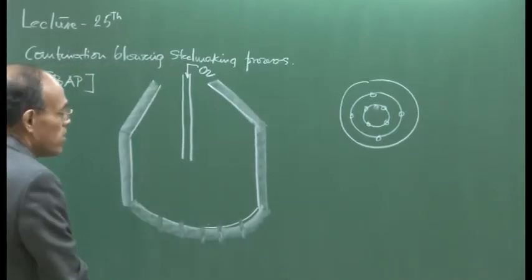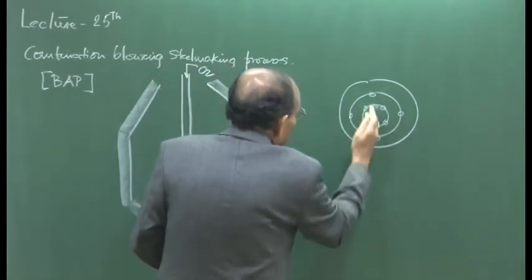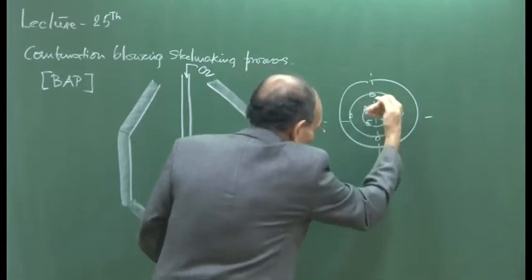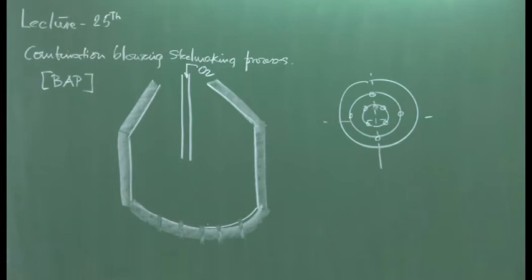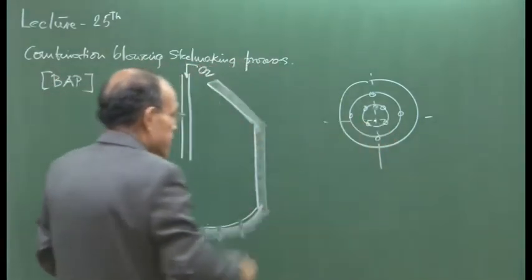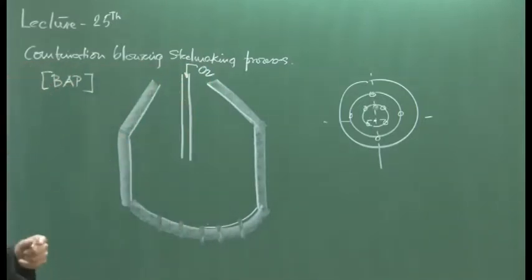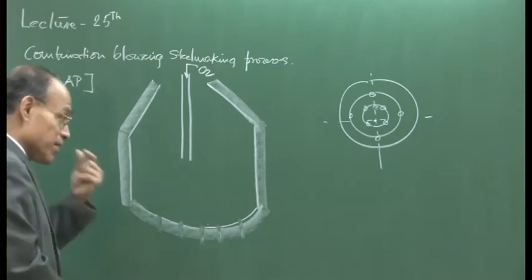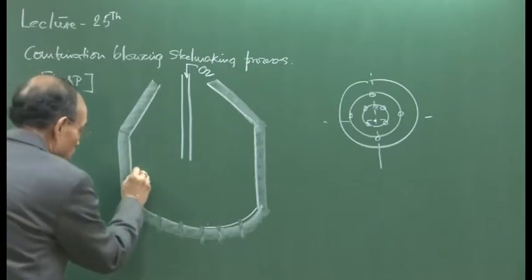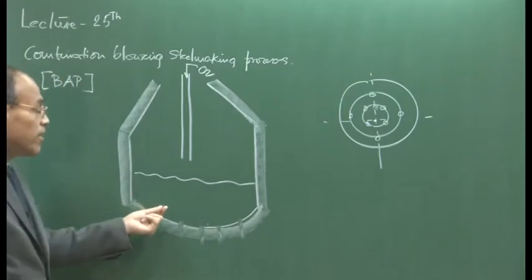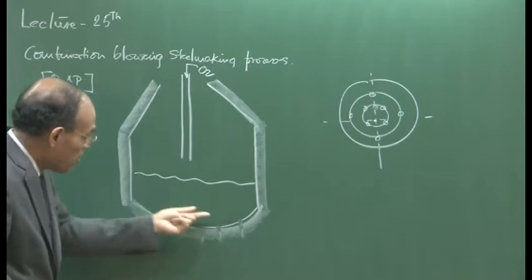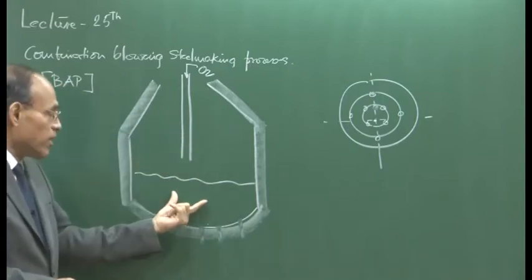When you inject oxygen with tuyeres, such an arrangement is rarely used — the tuyeres are located on one half if you draw a symmetrical plane, basically on one side of the central plane. The most frequently used arrangements are concentric arrangements, and not every converter will use 8 plugs. In the absence of any bottom stirring — as I have repeatedly said — the major disadvantage of the LD steelmaking process is that the reaction dominates in the top phase but there is not much stirring in the bottom part or in the bulk liquid.